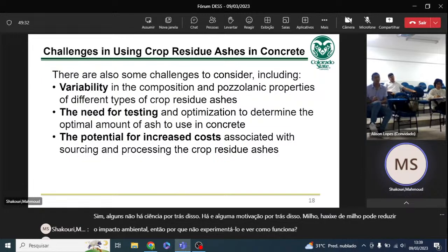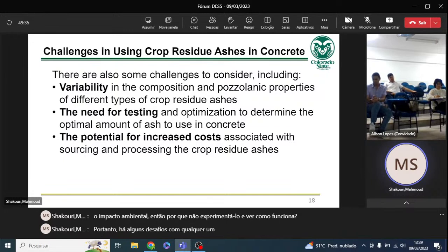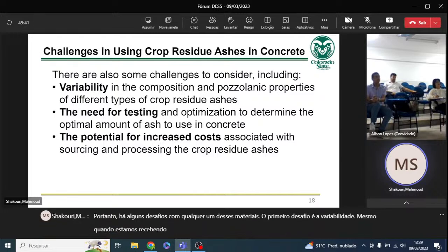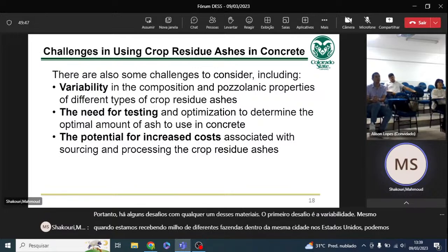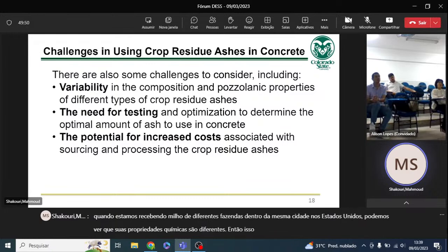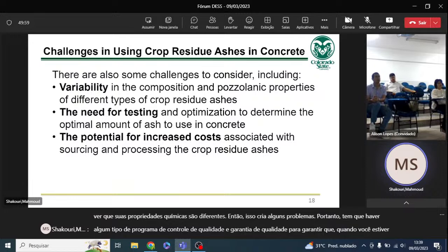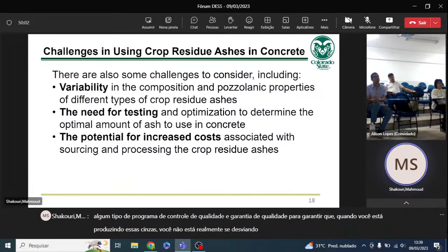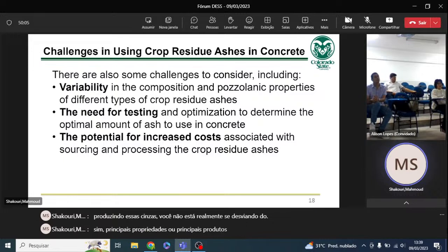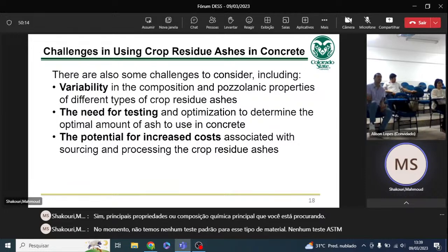So there are a couple of challenges with any of these materials. The first challenge is the variability. Even when we are getting corn from different farms within the same city in the United States, we can see that the ashes and their chemical properties are different. So that creates some issues. So there has to be some sort of a quality control and quality assurance program in place to make sure that when you're producing these ashes, you are not really deviating from the main properties or main chemical composition that you're looking for. Right now, we don't have any standard testing for these types of materials. No ASTM testing is there for plant-based ashes.